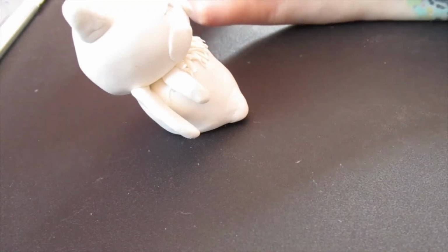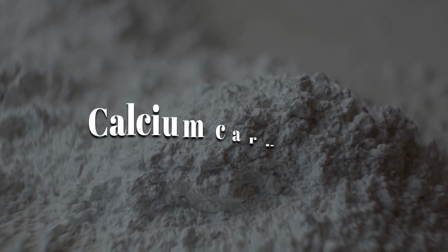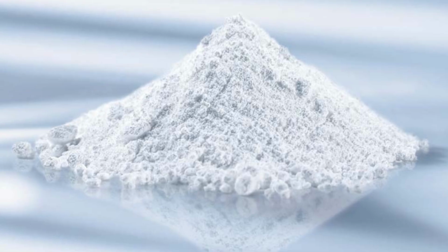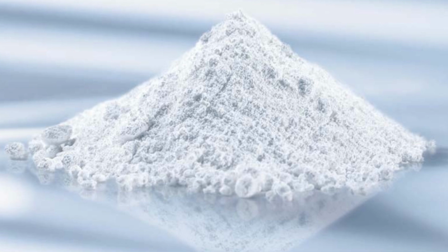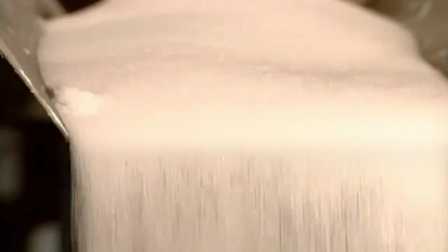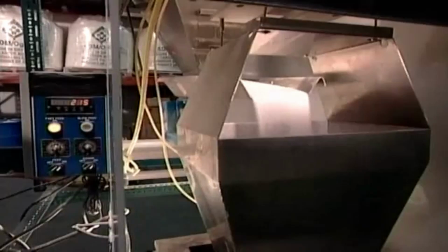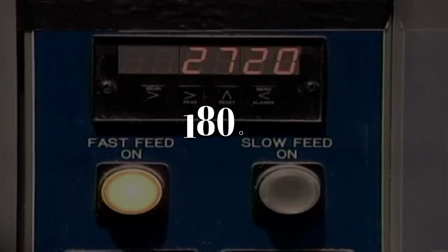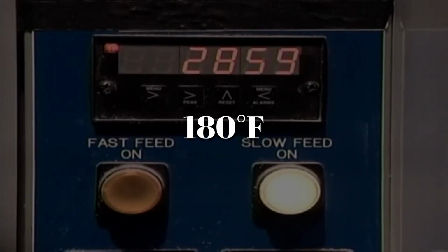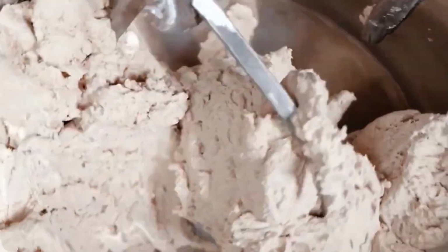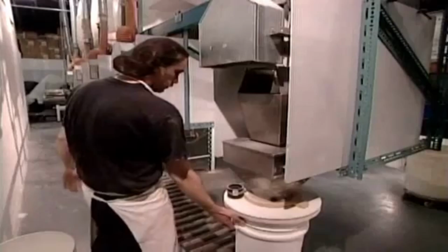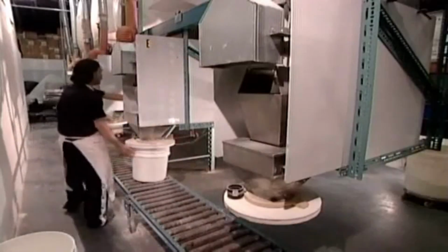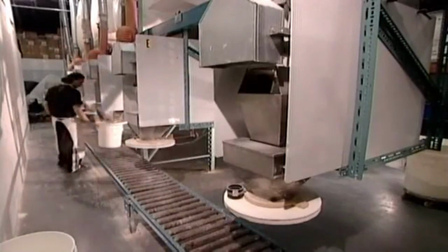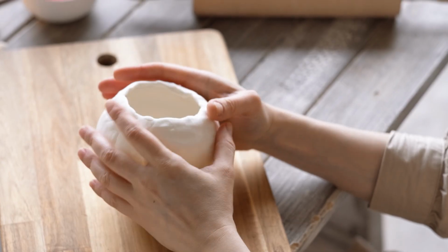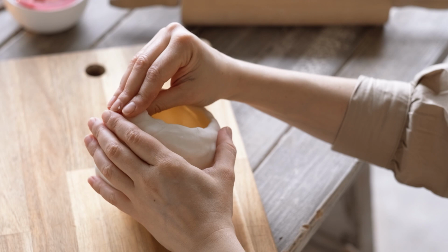To add structure and body, Crayola blends in calcium carbonate, a soft white mineral that also makes the clay more stable and dense. These ingredients are melted and mixed in large, heated industrial blenders at about 180 degrees Fahrenheit. At this stage, the mixture becomes a thick, creamy paste. But before it moves forward, it goes through a fine mesh filtering system to remove any air bubbles or impurities. That's what guarantees a lump-free, silky texture in every pack.